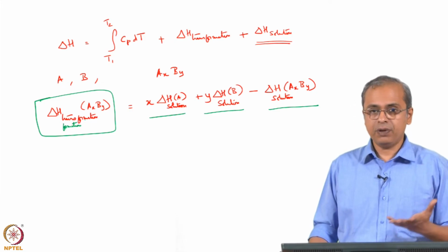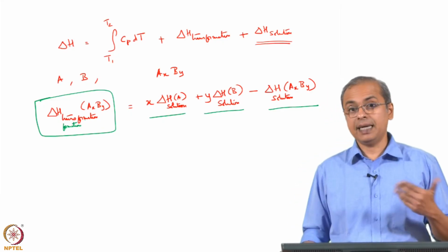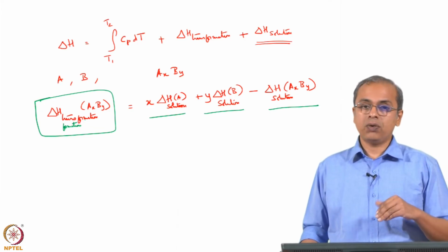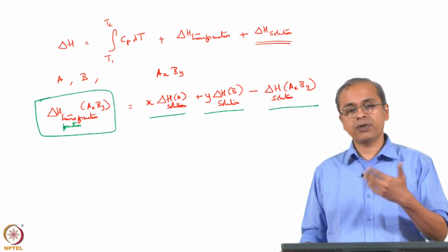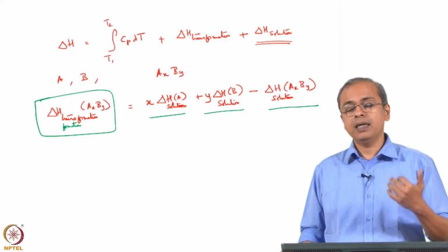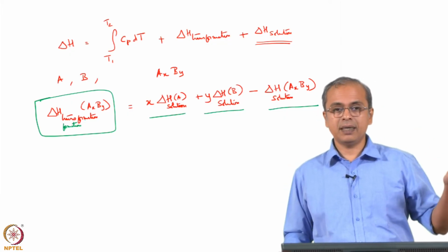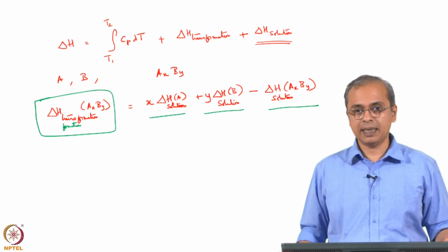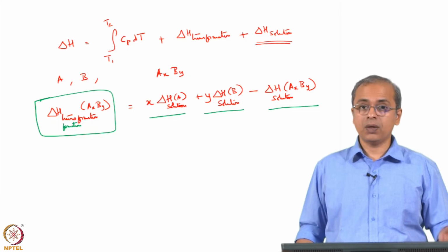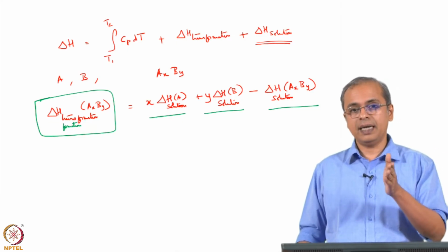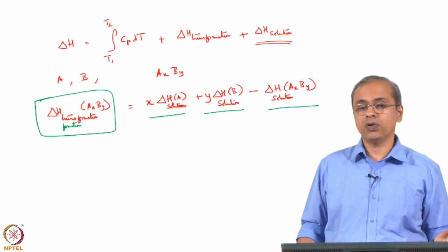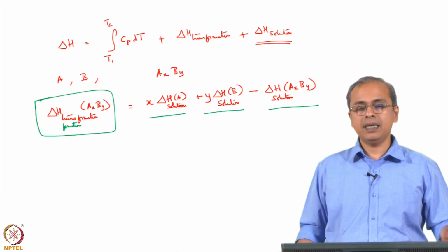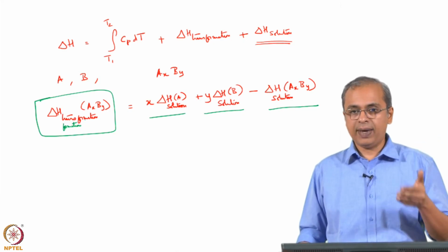One of the things you have to also be careful about is that, especially when you do calorimetry at the nanoscale, many materials, because they have high surface area, can be quite reactive, and often they may be hygroscopic. So, they may have pulled in some water. You have to account for the water also, because when you go from temperature T1 to T2, you are not just heating the sample, you are also heating things like the water associated with this sample. So, when you write this equation, you cannot simply write only for AxBy. You would also remember how many moles of water were present and account for it. Those are finer details that you need to look at when you do calorimetry, so that your equation gives you the value that you are looking for.